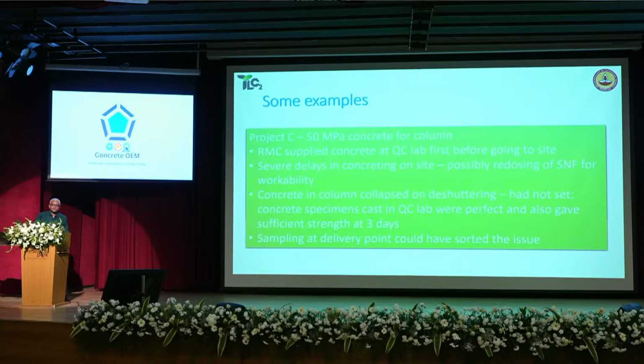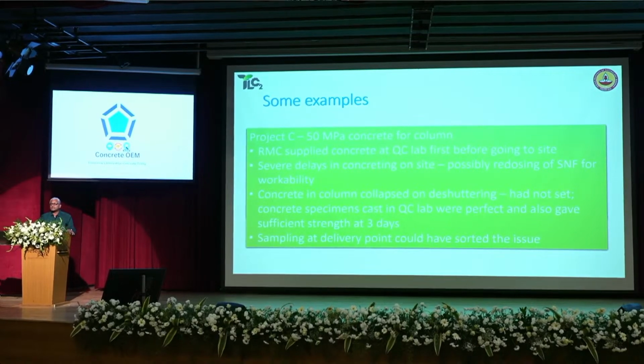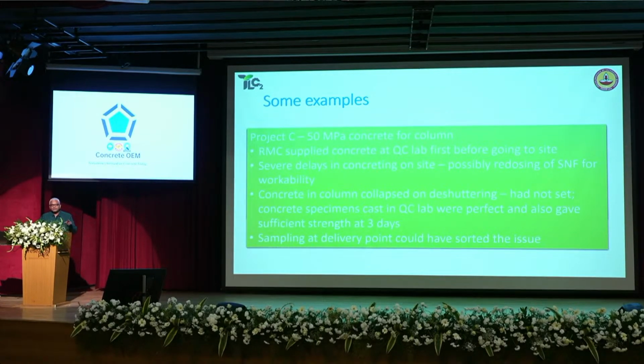Right? So this goes to show that, one, you need to ensure that the sampling for the strength is done at the point of discharge of the concrete. If the cubes had been prepared at the time of discharge, we would have understood that these cubes are not setting. Something is wrong with this concrete. Right? But instead of that, they opened the formwork, concrete collapsed. And two, the site needs to be prepared when the concrete is supplied.